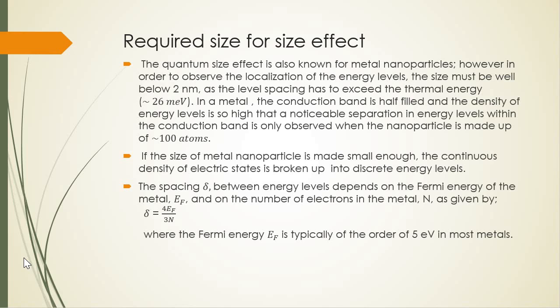The quantum size effect is also known for metal nanoparticles. However, in order to observe the localization of the energy levels, the size must be well below 2 nanometers, as the level spacing has to exceed the thermal energy, that is approximately 26 milli-electron volt. In a metal, the conduction band is half filled and the density of energy levels is so high that a noticeable separation in energy levels within the conduction band is only observed when the nanoparticle is made up of approximately 100 atoms.